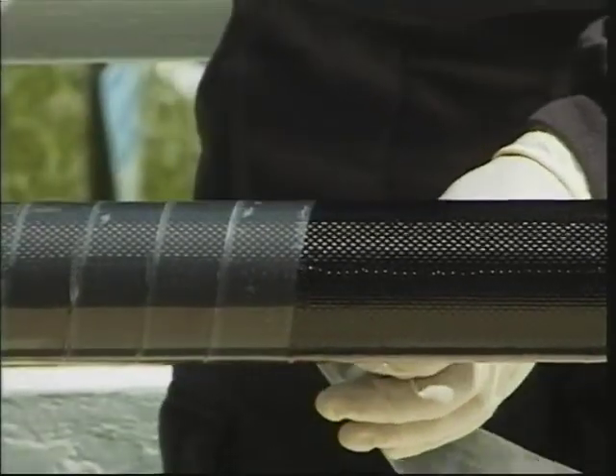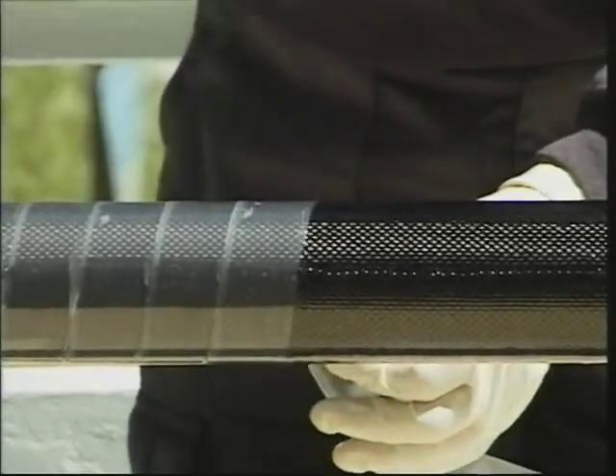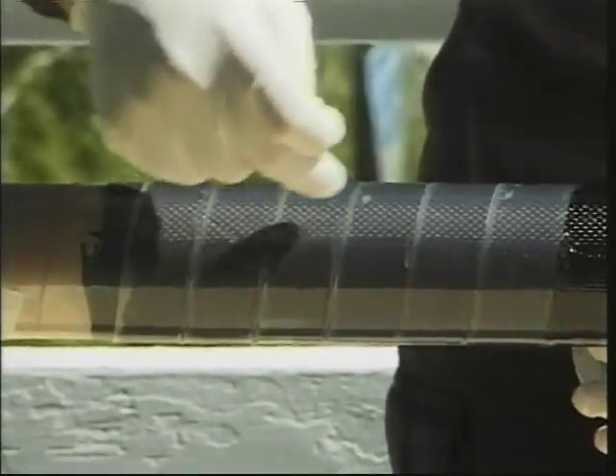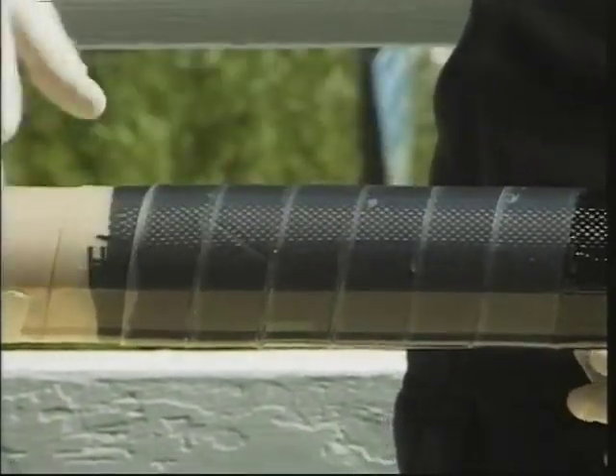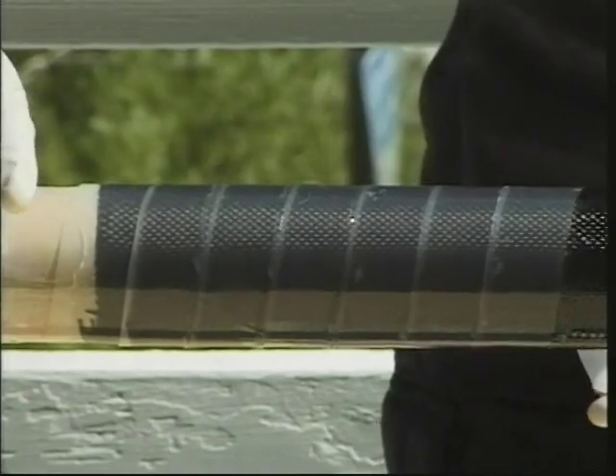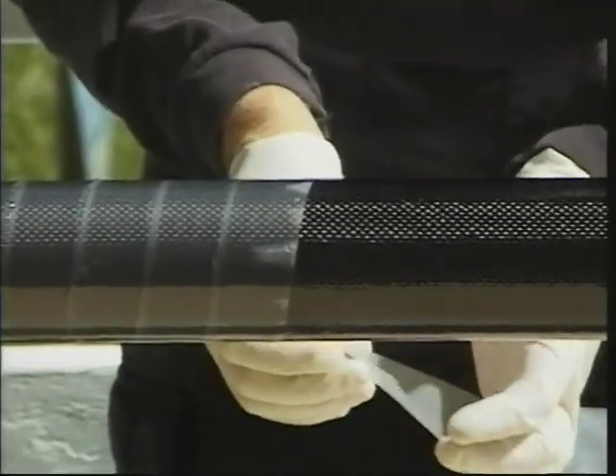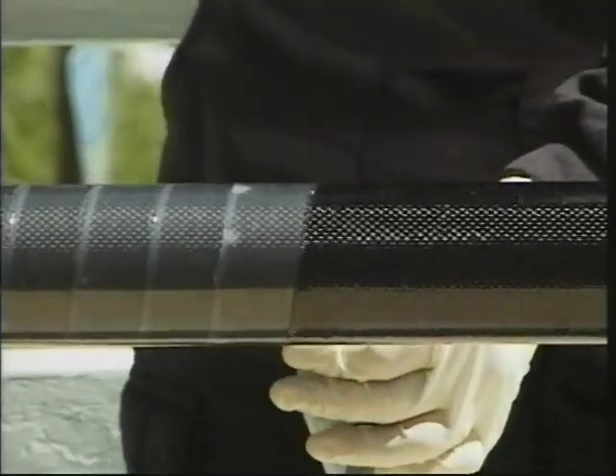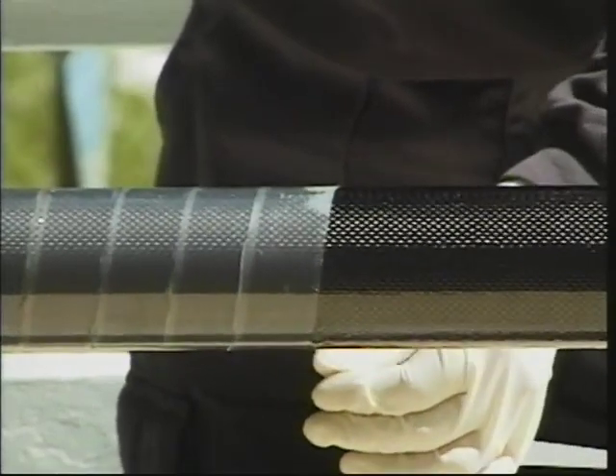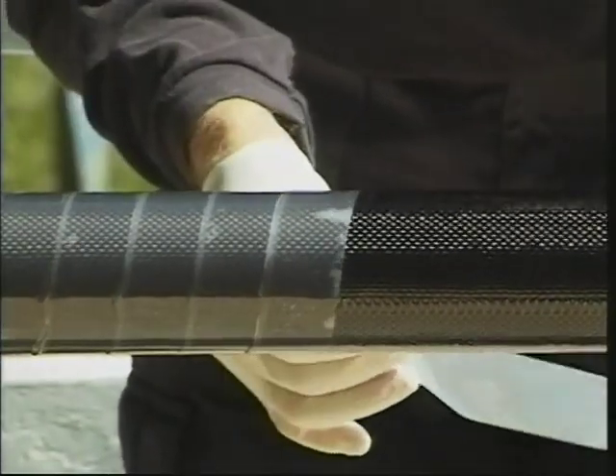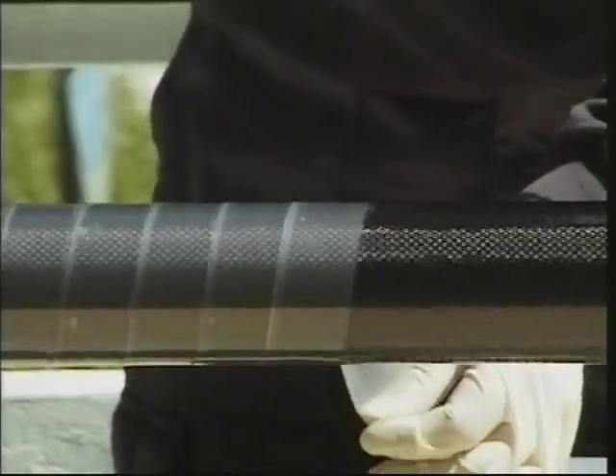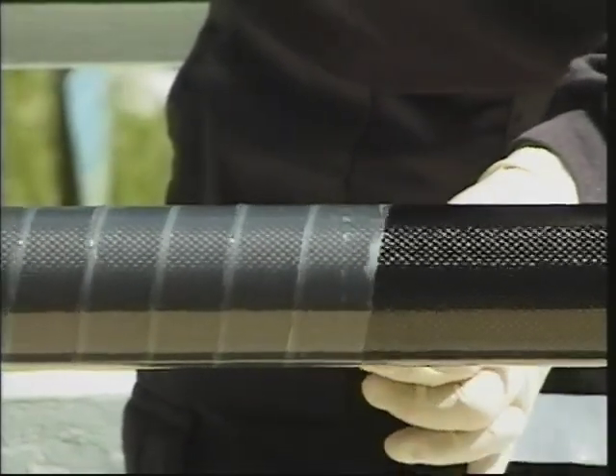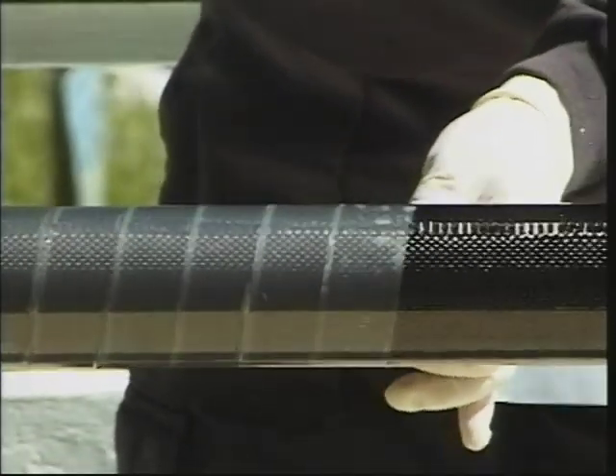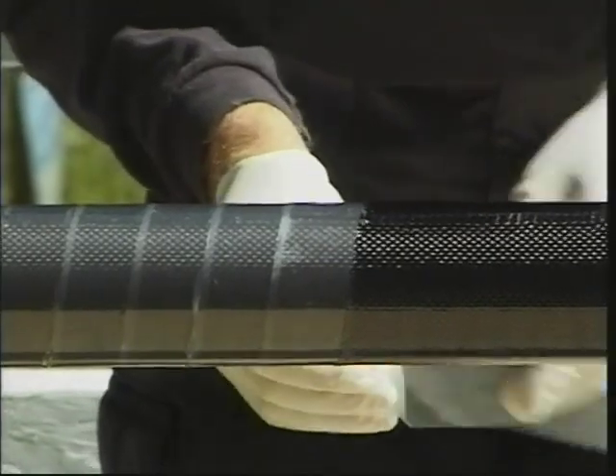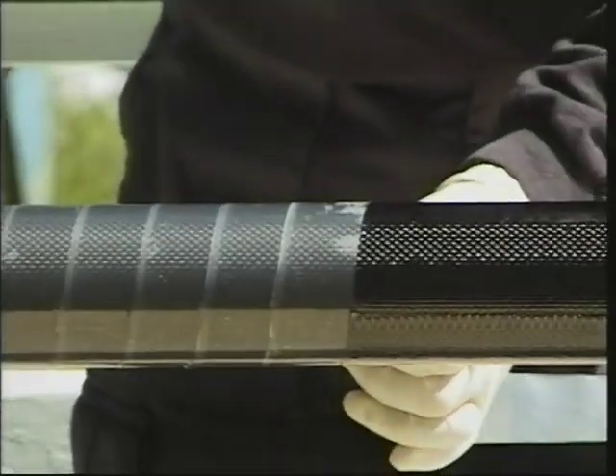Now you can see also, if we zoom in over here, resin is starting to drip out from between the layers of tape, just from the act of wrapping it. That's good. Again, I did add that excess resin so that all of these individual carbon fibers will be encapsulated and mingled with that resin in the laminate, which will give us our tremendous strength.